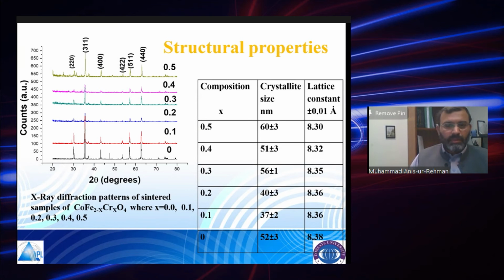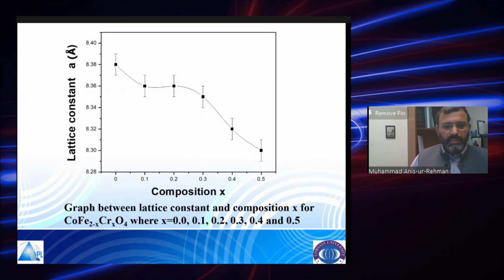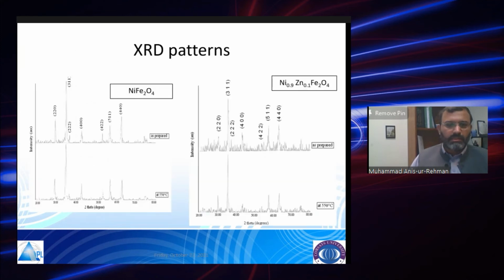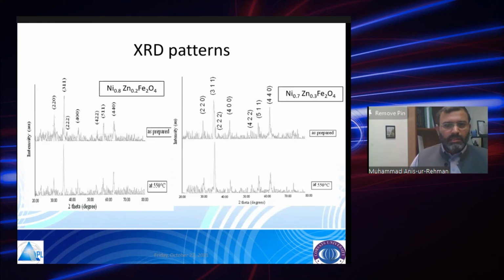We got the single phase cubic structure in all the cases, and as we are increasing the concentration, the lattice constant is decreasing due to the reason that chromium has a smaller ionic radius as compared to iron, so the lattice is contracting. These XRD patterns are indicating the same thing.